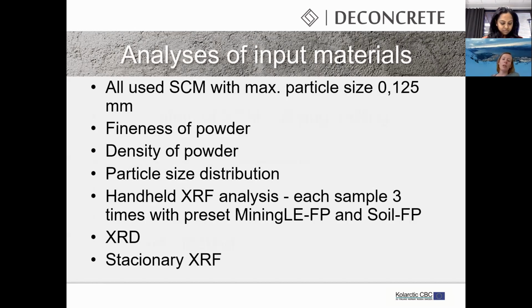As was mentioned, all were under 0.125 millimeters. Fineness of powders, density, and particle size distribution were evaluated, and then also the chemical composition by handheld XRF and stationary XRF, and then mineralogy was analyzed by XRD.